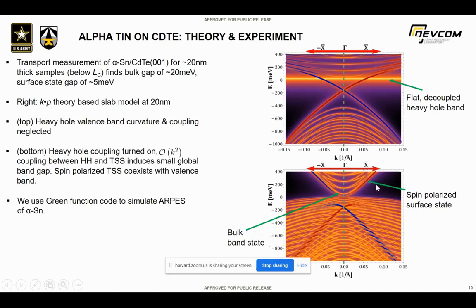You can actually see the spin polarized surface states and the Dirac point more clearly if you turn off the heavy hole details. Nevertheless, you can see that at this thickness, which is around 200 angstroms on a cadmium telluride substrate, you have a Dirac crossing and the Dirac cone is formed quite clearly if you just remove the heavy hole coupling for a while. If you put it in, it's hard to discern, but it's still there. It's actually degenerate with the heavy hole band structure, the gamma 8 heavy hole band structure. So it's hard to see in a typical measurement. But all these details are related primarily to the heavy hole band structure.